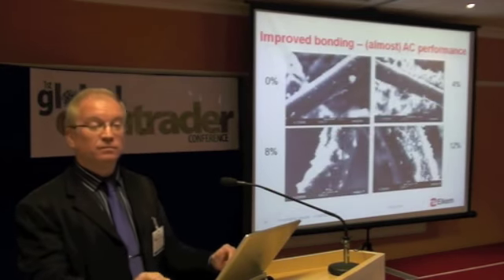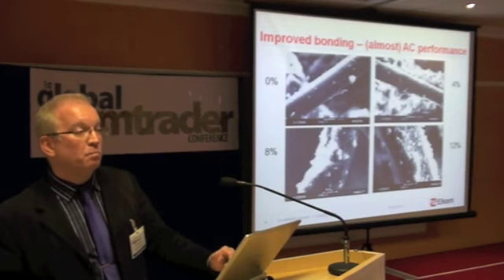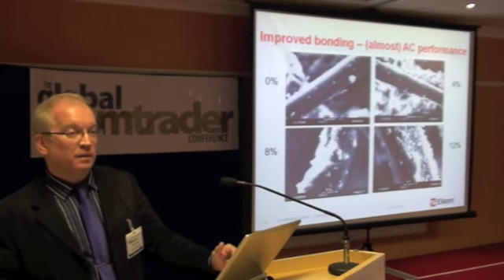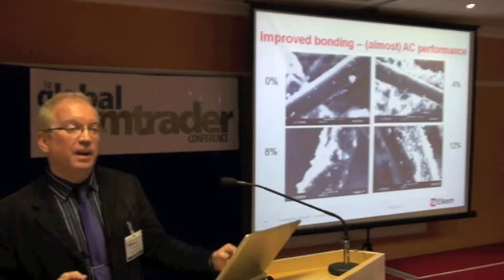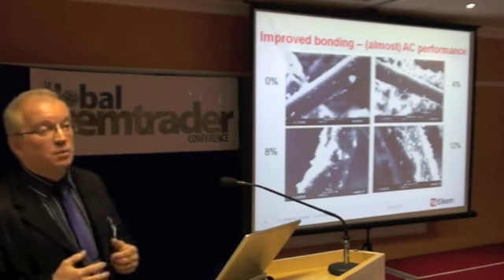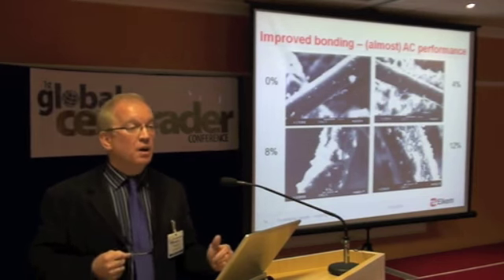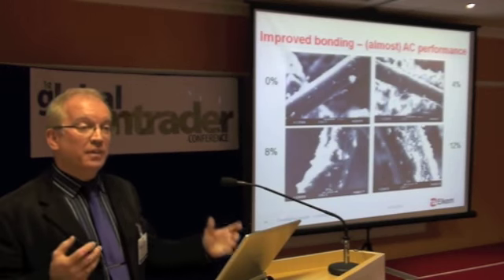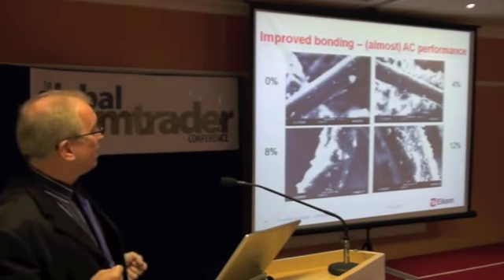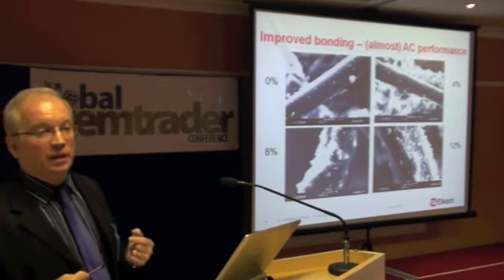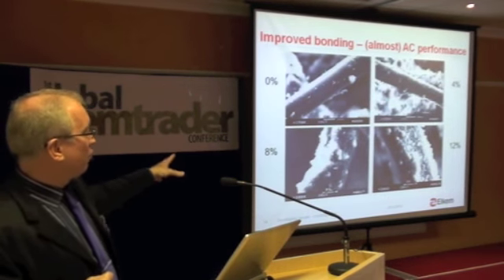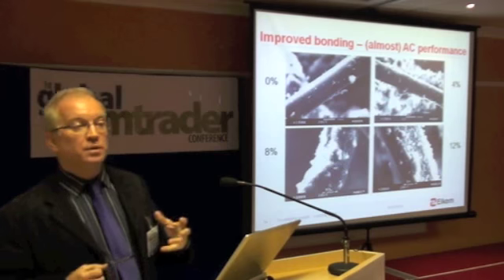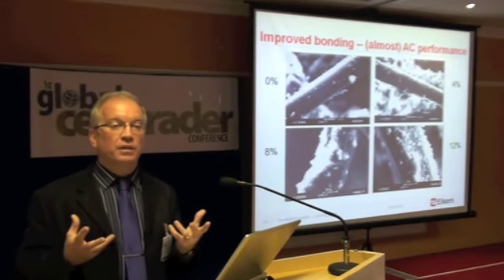It works because they can get the bond. The bond to the fibres is the key factor, the important factor. Here you can see what happens as you add different amounts of the silica fume to that mix. You can see that the fibre is virtually uncoated in the first one. A little bit more, 4%, but around 8 to 12%, you've got a very good coating on that fibre.